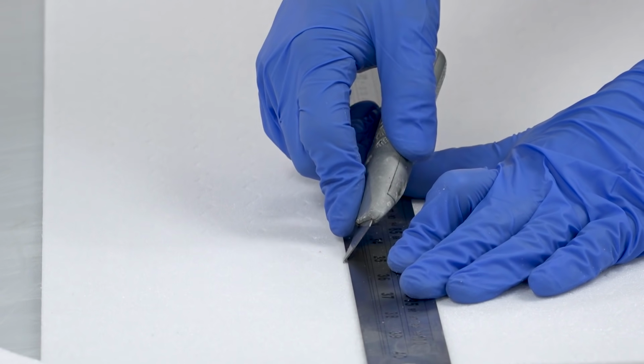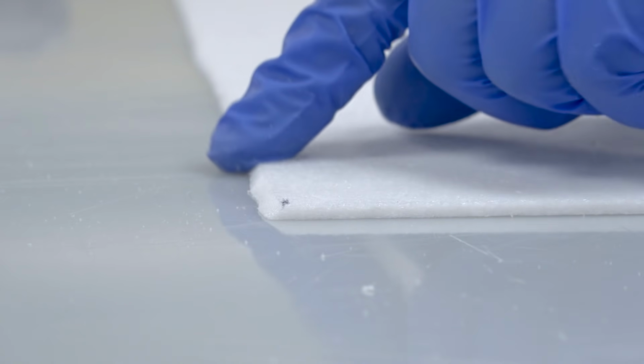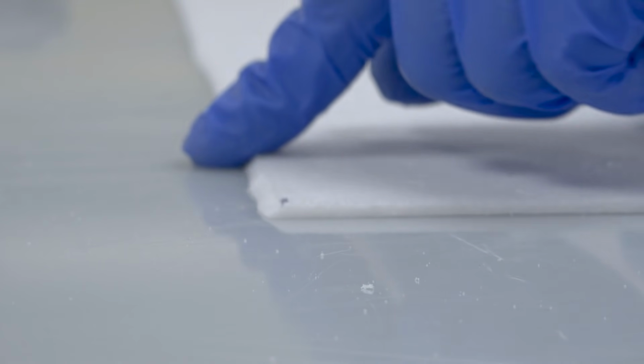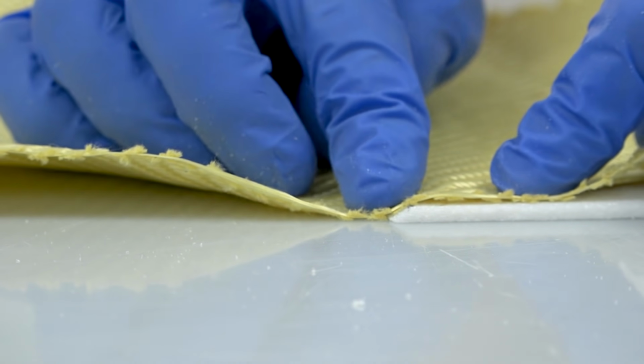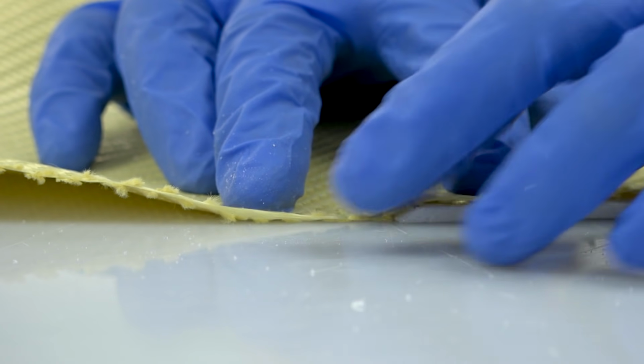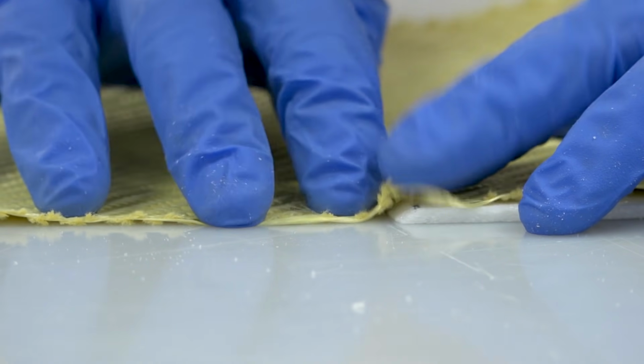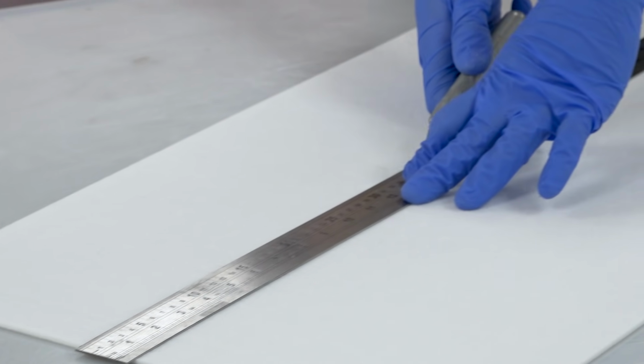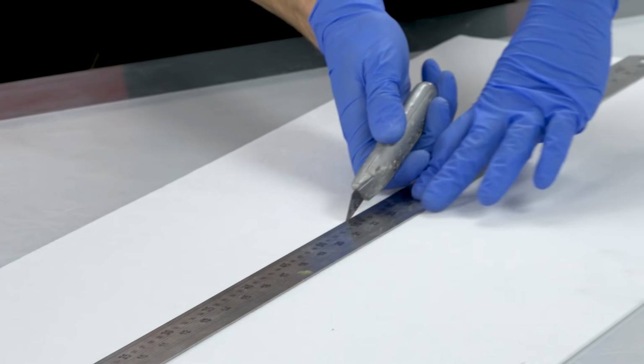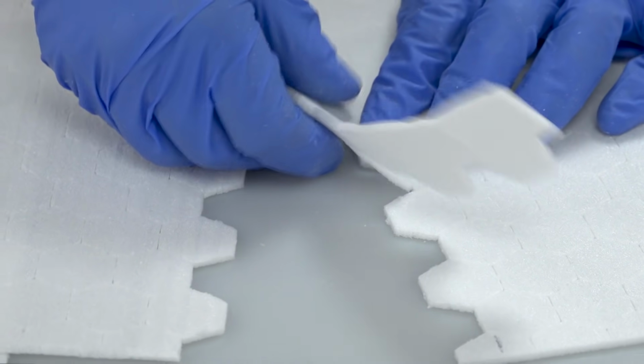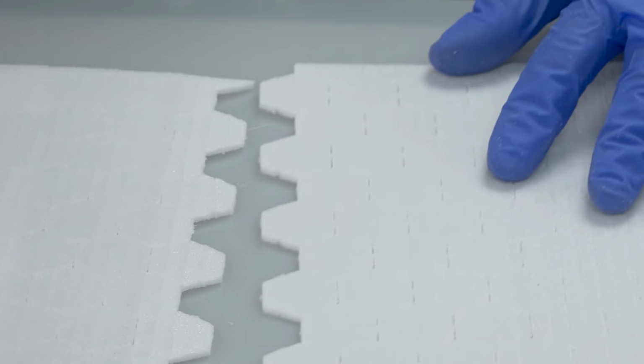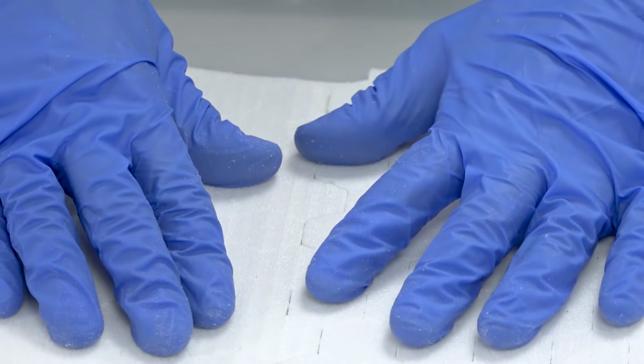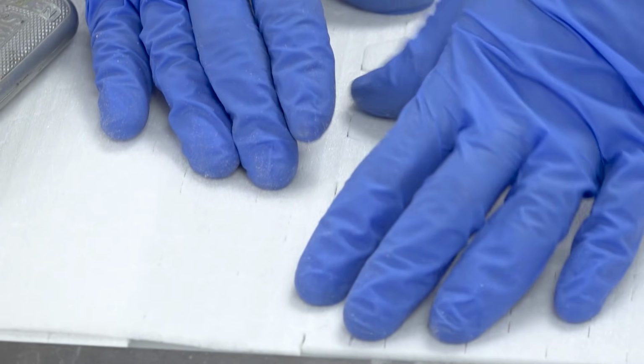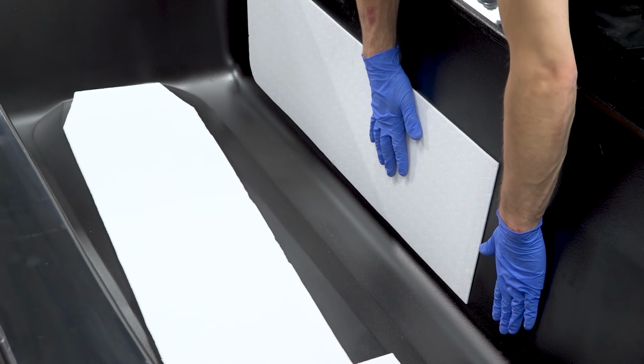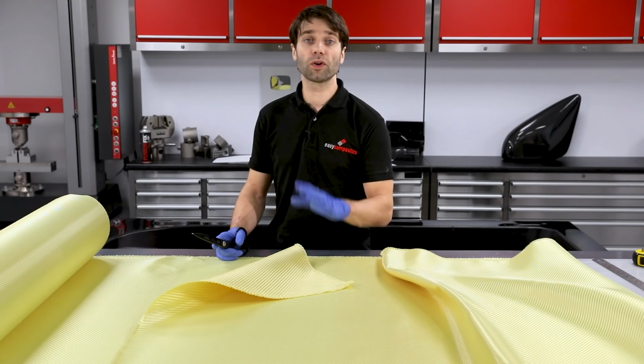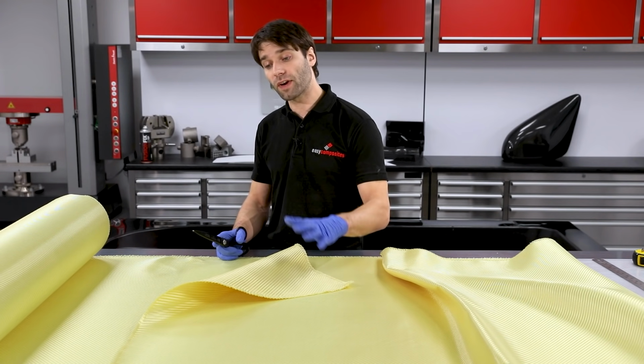The edges of the core material should be chamfered. This tapered edge will allow the layers of fabric to follow the edge without any sharp changes in direction and without leaving a bridge void that could lead to an inconsistent infusion. 3D core is manufactured in relatively small sheets, but joining them together is a simple process of breaking out the hexagons and nesting them together. This has no significant influence on either the infusion process or the structural properties of the part. With the core materials prepared, we're now going to cut the reinforcement itself.